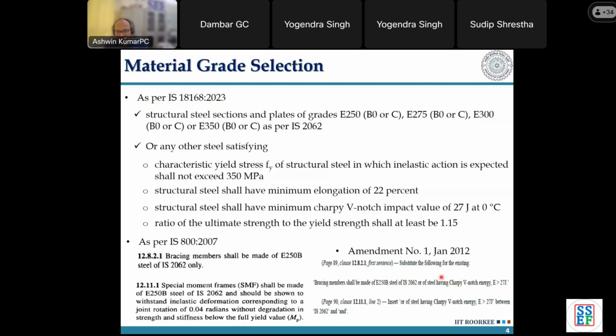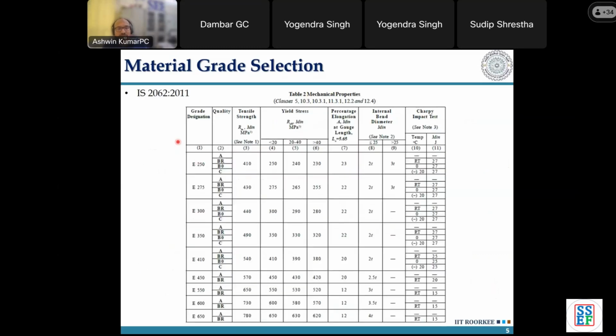But by the inclusion of this particular line, steel having a Charpy V-notch energy greater than 27 joules, it opened up a possibility for steel makers and manufacturers to supply steel of higher strength. So if I show you IS 2062, which I said highlights the chemical and mechanical properties of the structural carbon steel that is available in India. First of all, you can see that the grade is from E250 to E650, but currently our code limits our use of grade of steel to E350 only. So when you see E250, whereas E350, the minimum Charpy V-notch energy at 0 degrees Celsius is mentioned as 27 joules minimum.